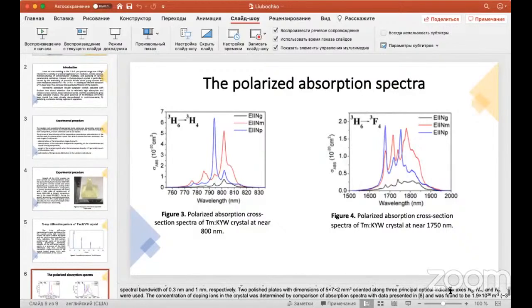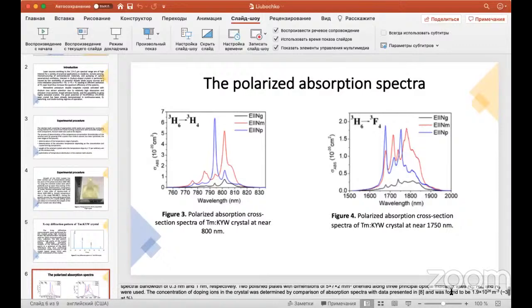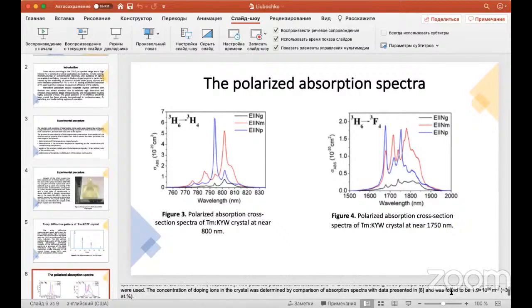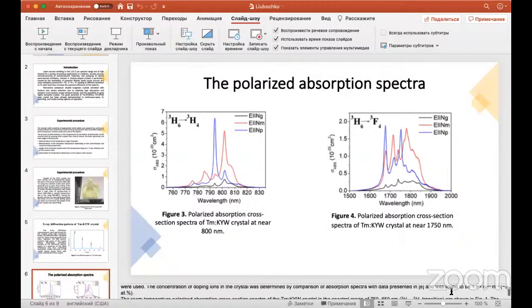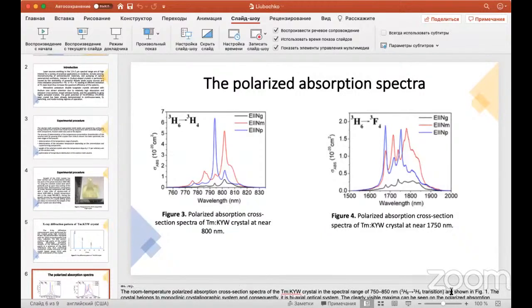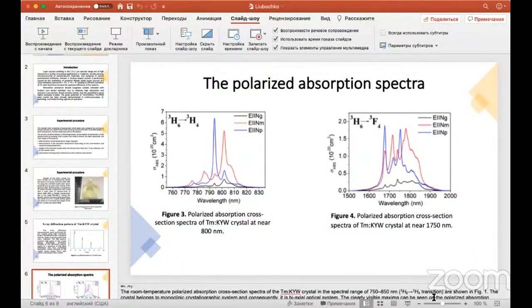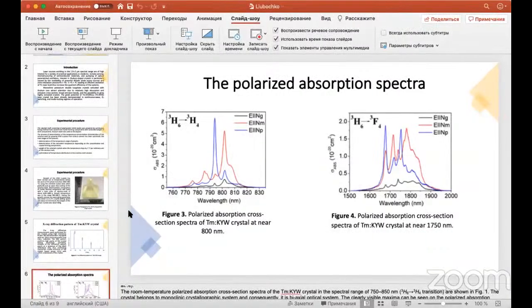The concentration of doping ions in the crystal was determined by comparison of absorption spectra with data and was found to be 1.9 times 10 to the 20 per cubic centimeter. The room temperature polarized absorption cross-section spectra of the Tm:KYW crystals in the spectral range 750 to 850 nanometers are shown in figure 3.